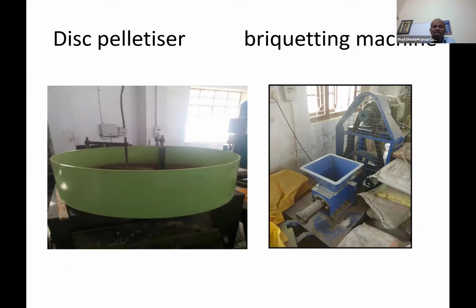This is a briquetting machine. After it is mixed, we manufacture it in the briquetting machine. So first the mixing is done with the disc pelletizer or mixing machine, then we have done the briquetting, then we have put it into sintering at 1250.